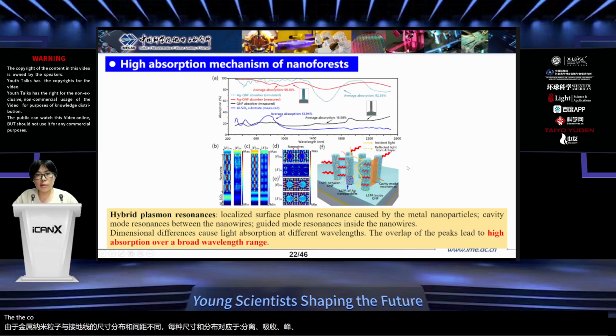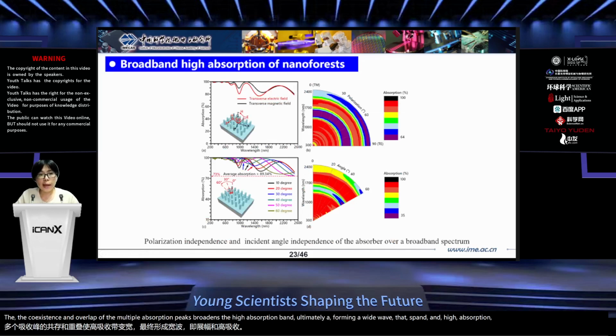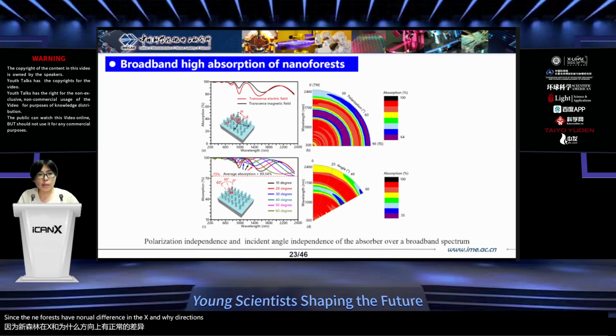The coexistence and overlap of the multiple absorption peaks broadens the high absorption band, ultimately forming a wide wavelength band and high absorption. Since the nanoforests have no structural difference in the X and Y directions, the light absorption characteristics of the nanoforests are not sensitive to polarization. In addition, due to the large aspect ratio of the nanoforests, the light trapping effect is also insensitive to the angles of the incident light. From these two perspectives, we can say that the nanoforest is naturally a perfect light absorber.